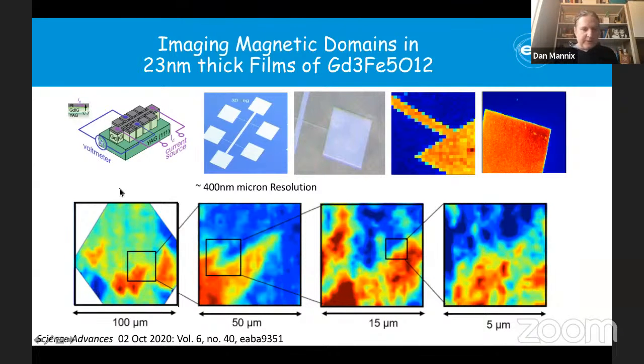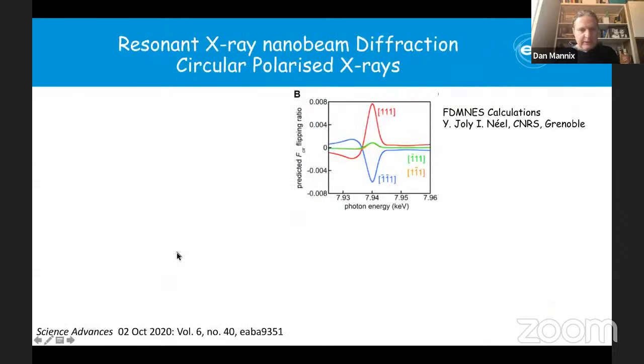So this is like the 100 micron size, looking at those big pads, just scanning around and mapping out where these contrasts come from. This is now a 15 micrometer zoom. So we zoom in again into these regions, down to 15 micrometers, and then we can go all the way down to 5 micrometer length scales. And it looks like there's a very large distribution in domain sizes, going all the way down even to the sub-micron size in these materials. So that's actually quite interesting. We couldn't resolve them any further than our resolution, our beam size, but they exist on very short length scales in these materials. So that's the first kind of result we get.